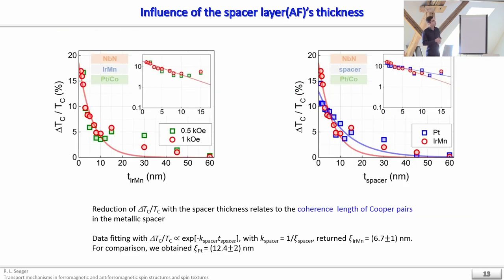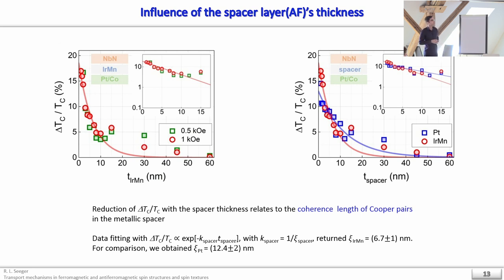We also investigated what happens with a spacer layer — iridium manganese — between the ferromagnet and the superconductor. We see a reduction in the critical temperature recovery as a function of the spacer thickness, because Cooper pairs have a finite penetration depth. When the IrMn layer is thicker than a certain value, the Cooper pairs cannot reach the ferromagnetic layer and the partial recovery of critical temperature is lost. By fitting this data we obtain a coherence length for iridium manganese of around 7 nanometers, compared to approximately 12 nanometers for platinum.